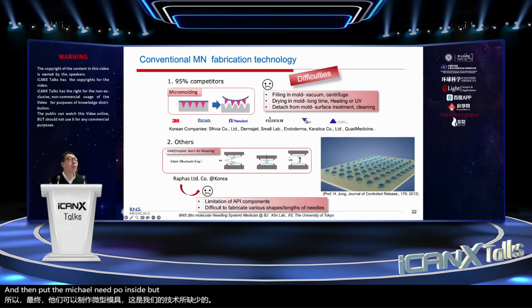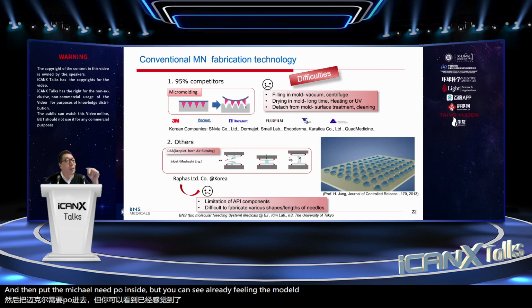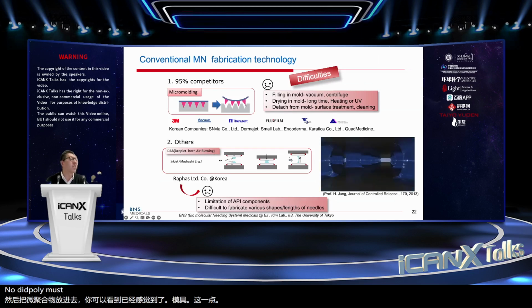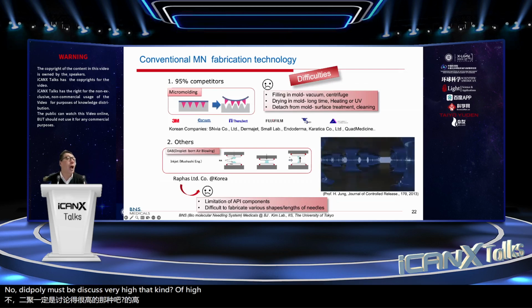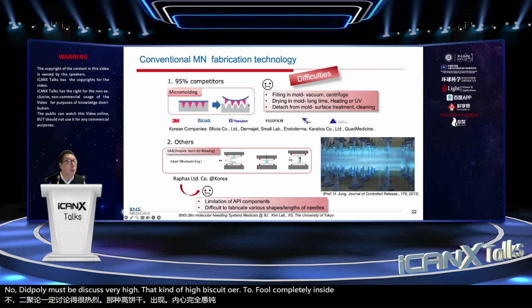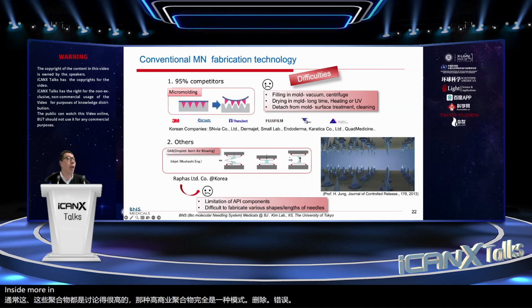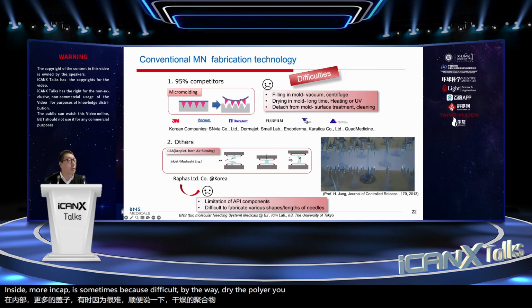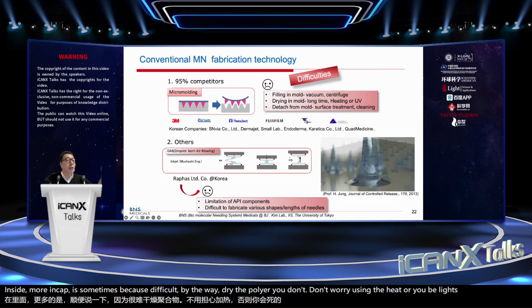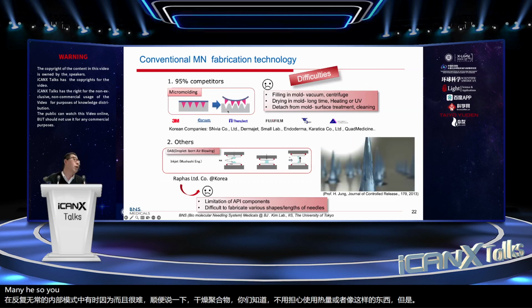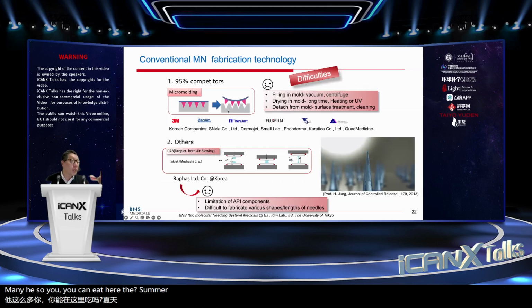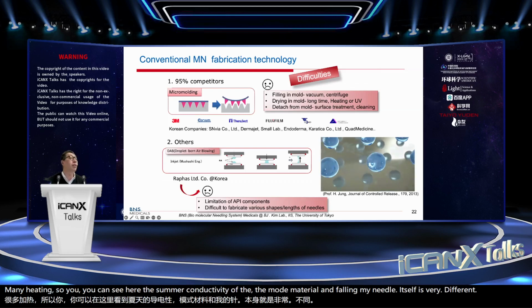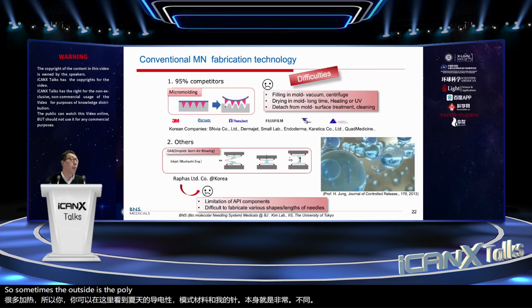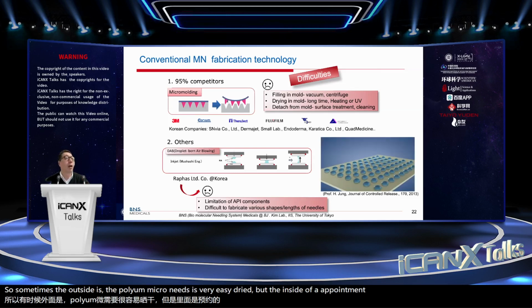But you can see already that filling the mold is hard, because normally this polymer has very high viscosity. It is sometimes difficult for that kind of high viscosity polymer to fill the mold completely and to remove the air inside the mold cavity. By the way, to dry the polymer you normally use heat or UV light, mainly heating. So you can see here the thermal conductivity of the mold material and the polymer needle itself is very different. So sometimes the outside of the polymer microneedle dries very easily, but the inside of the polymer sometimes takes more time.